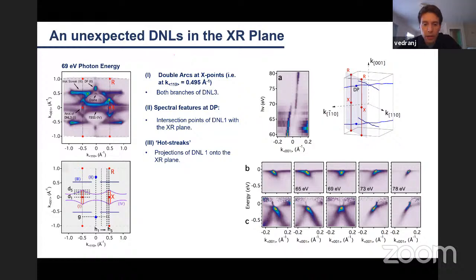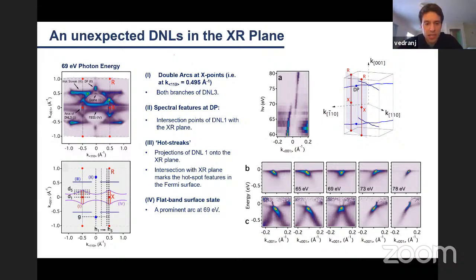And finally, you can then see the prominent arcs of the flat band surface state anchored between these Dirac nodal lines. So this is really a surface state, whereas the Dirac nodal lines are bulk features in this material.